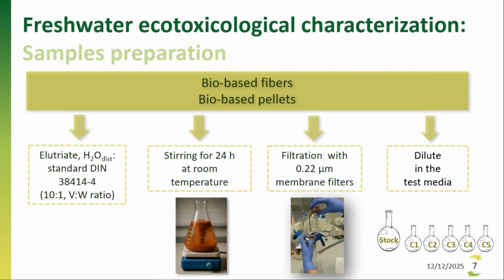For the remaining formats, we have performed 24-hour liquids or eluate suspensions that were prepared to mimic potential release of contaminants or nutrients from these solid materials into a liquid phase. For the bio-based fibers and for the bio-based pellets, we have followed the available German standard method for the examination of water, wastewater, and sludge that indicates that these materials have to be deployed in distilled water at a proportion of 10:1 in terms of volume to weight. They are left to stir for 24 hours at room temperature, after which they are filtered by a 0.22 micrometer membrane and then are diluted according to the desired dilutions that we want, using media proper for each freshwater species.